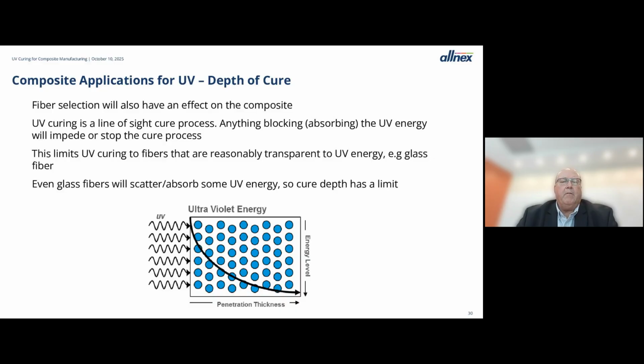So fiber selection is going to have an effect on the composite. And this pretty much means you have to use glass fibers. If you try to do UV curing with a carbon fiber composite, the fibers just pretty much absorb all the UV energy, and you can't really get any kind of through cure in a composite. So if you want to go with UV, you pretty much are going to be using a glass fiber because the glass is reasonably transparent to the UV. Even so, as you can see in the bottom picture there, the thicker you go into the composite, the lower the energy level is, and the slower the cure is going to be. So there's a practical limit to how thick you can make a glass fiber composite.